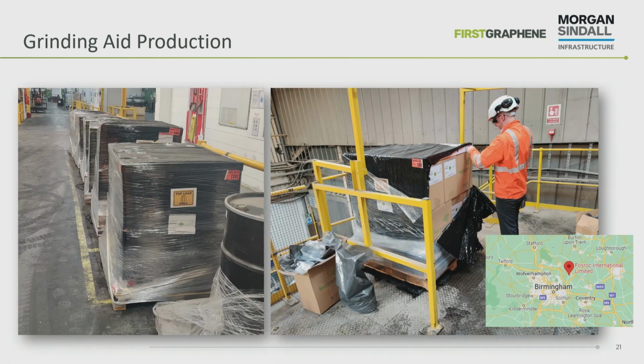Then this is our graphene, the 7 or 8 pallets of graphene which was dispersed into that grinding aid. So that's the pallets on the left of graphene, someone unpacking the pallets on the right, and that just went into a big tank and was loosely mixed. It was a powder in those boxes, powdered graphene, that went into the mixer, just a paddle mixer. Again, no high shear, no dispersion, really just mixing it round so that it was in a liquid and easy to handle by the pumps.